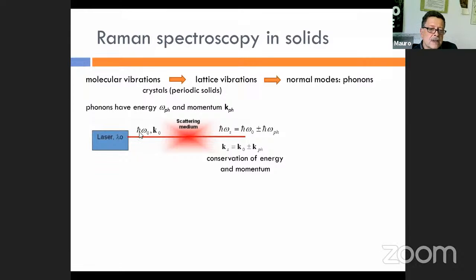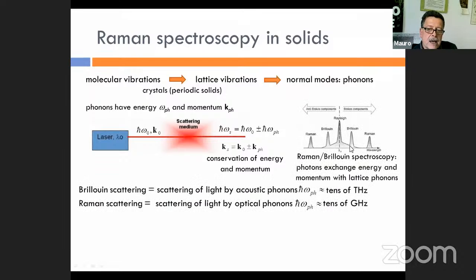So when there is the interaction between the incoming photon and the material, we need to conserve energy and momentum in the scattering process. Since in a generic solid we have acoustic and optical phonons, we can have scattering both from the acoustical branch, and this is named Brillouin scattering, and we can have scattering by the optical phonon branch, and this is the true Raman scattering. The two processes have quite a different frequency scale, so it is very difficult to make a Brillouin spectroscopy measurement. The instrument needs to be really different from the Raman one, so we will refer to Raman spectroscopy only in the following.